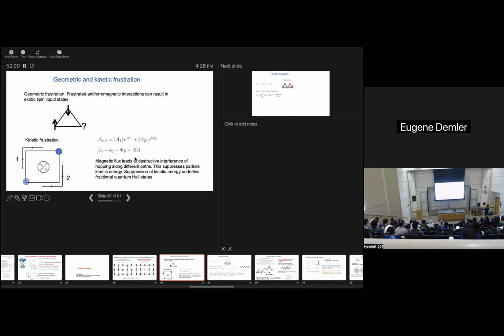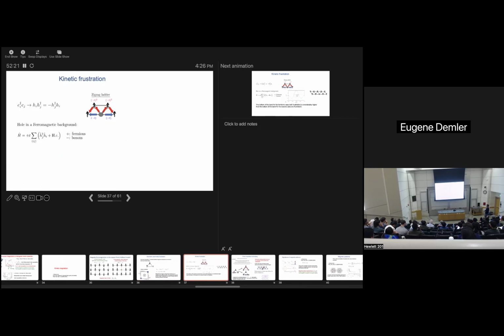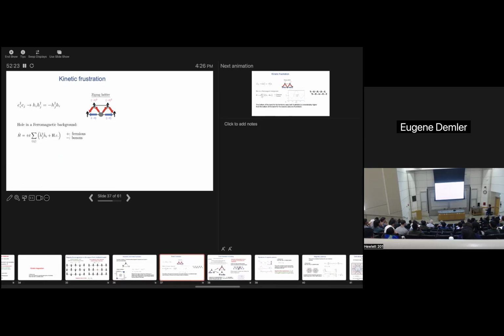And so if this flux is large, particularly if it is close to pi, we can get very strong destructive interference. And that's actually the idea of why we get this flat Landau level in the quantum Hall effect, where effectively kinetic energy is suppressed because the different ways of the particle moving all interfere destructively. But do we need a magnetic field in order to get frustration? Well, let me show you that there is an example which is relatively simple without a magnetic field.